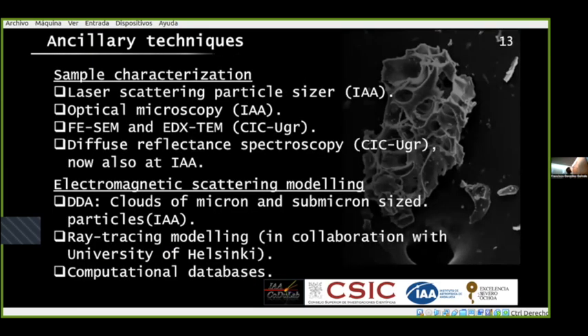And this is complemented with a number of ancillary techniques. We do laser scattering particle sizing for determining the size distributions, and optical microscopy also to determine size distributions. We do scanning electron microscopy or transmission electron microscopy. We do energy dispersive X-ray spectroscopy to determine the composition. And we also do diffuse reflectance spectroscopy measurements. And we now have this facility at the IAA to determine the mineralogy.